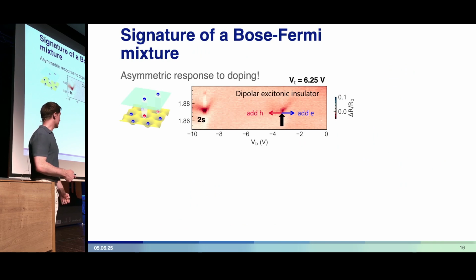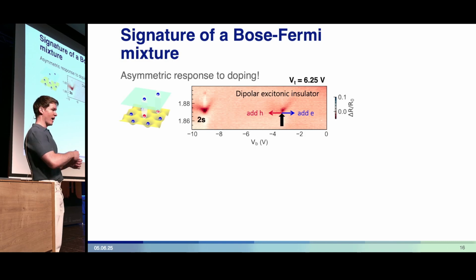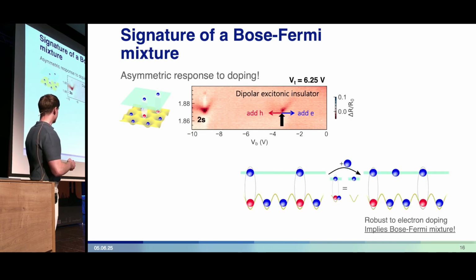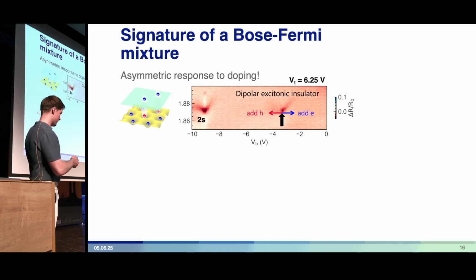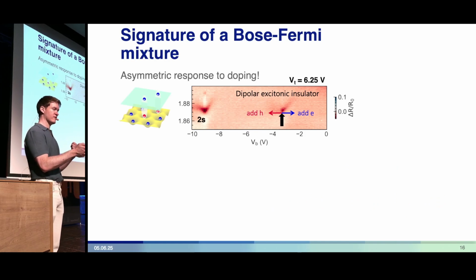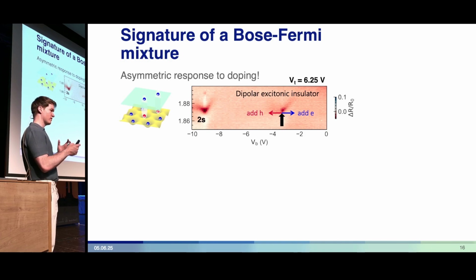Finally, I want to examine what happens when we start with the dipolar excitonic insulator and we either add some electrons or remove some electrons from the system. You can see that if we track the 2s exciton and add electrons, there's a continuous loss of 2s exciton signal strength. This means the screening of the system is just gradually changing, the compressibility is changing gradually.